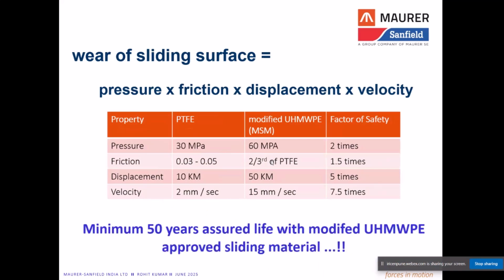In addition to all these things, there is one advantage with this bearing during inspection. In the case of a pot PTFE bearing, everything is inside the bearing, like the rubber, which is made of chloroprene or natural rubber, confined within a steel cylinder. So at the time of inspection, the authority has no idea what exactly happened inside the bearing, or whether any sealing failure has happened. But in the case of a spherical bearing, everything is exposed at the surface of the bearing, so there is no hidden part inside it. That will also be a better solution during the inspection of the bearing. Now, with the help of this modified material, we can achieve the highest lifespan of the bearing, and it is also suitable for higher displacement and friction velocities.